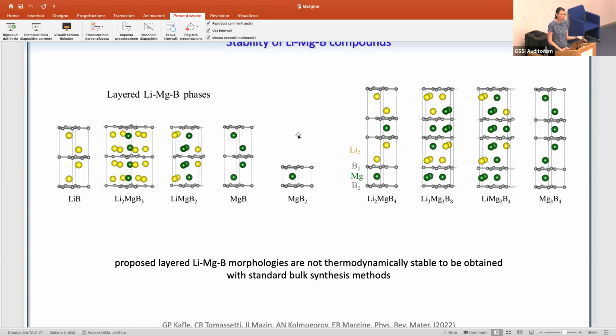Nevertheless, because here we were interested in understanding beneficial features for MgB2 superconductivity, we picked two of these hypothetical systems. Particularly, we looked at magnesium boron, which is the sister compound of lithium boron, and also at lithium MgB2, this compound here, which as you can see is a bridge between lithium boron and MgB, and also was the smallest predicted structure in our calculation. The other configurations have many more atoms in the unit cell, and we did not investigate them at this point.